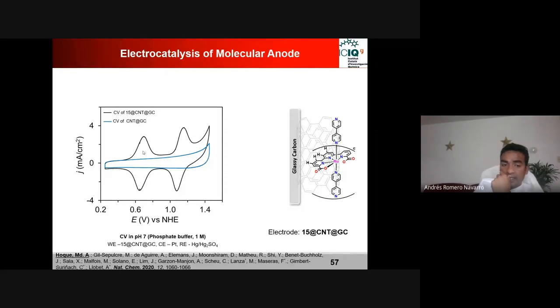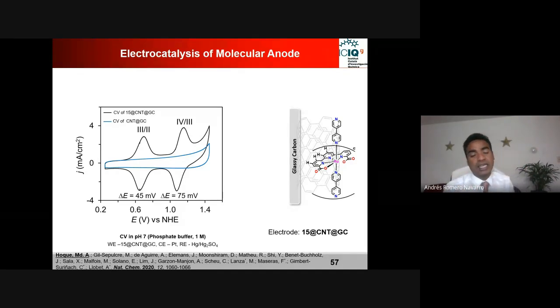So now we see the two redox couples. This is the ruthenium 2/3 and this is the 3/4 redox couple for this compound, and it is known because its mononuclear unit has already been published. And the redox potentials are perfectly matching with this system. And then we knew that this is not the real catalyst.